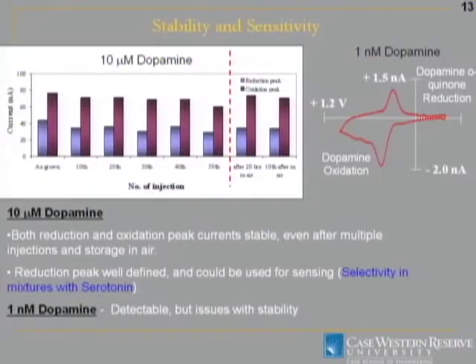In terms of the stability of this response, for a larger concentration of dopamine, here's 10 micromolar dopamine. The purple scan is the oxidation peak, injected about 50 times. My student went home, got some sleep for some reason, came back, and he didn't have to polish the electrode, rinse the electrode thoroughly, do any kind of cleaning. He put it back in the electrolyte, and he got the dopamine signal right back, which this is, of course, just over a couple of days.